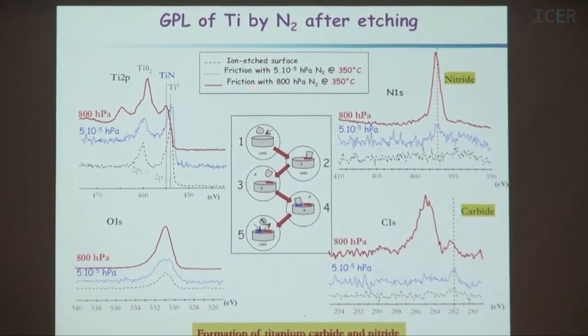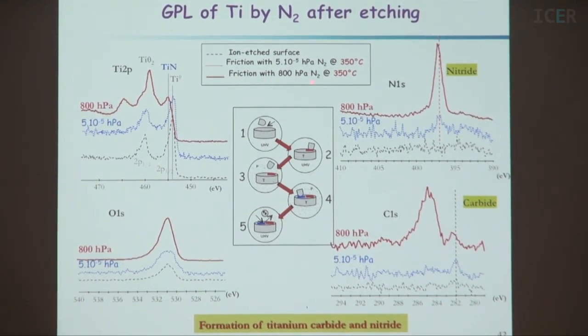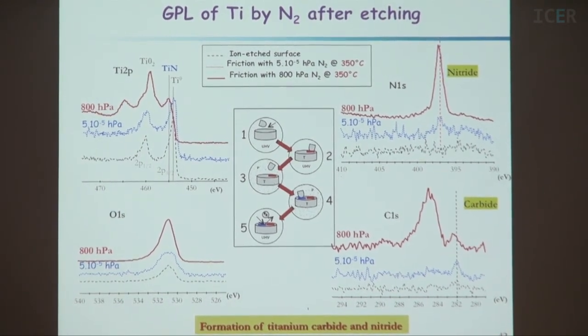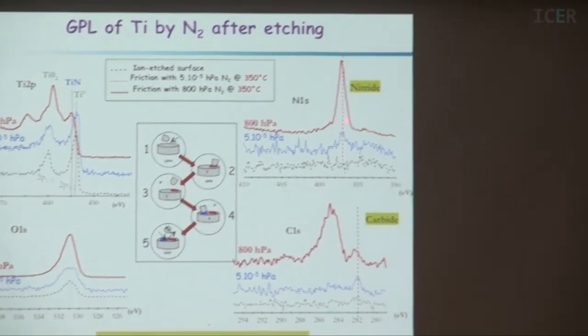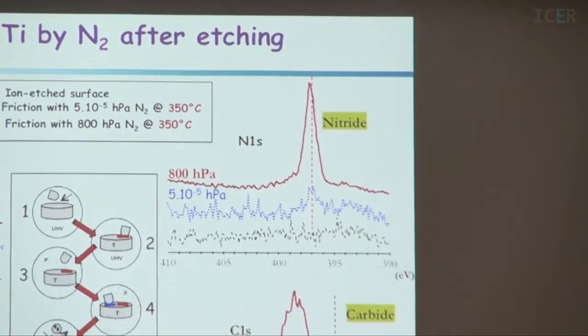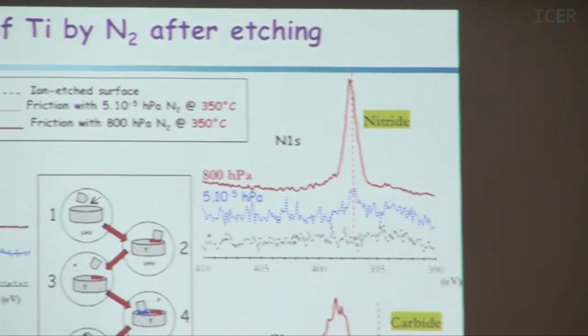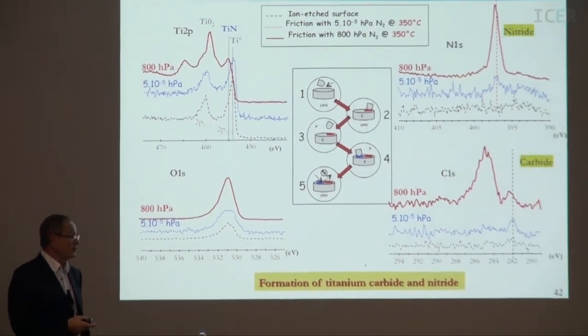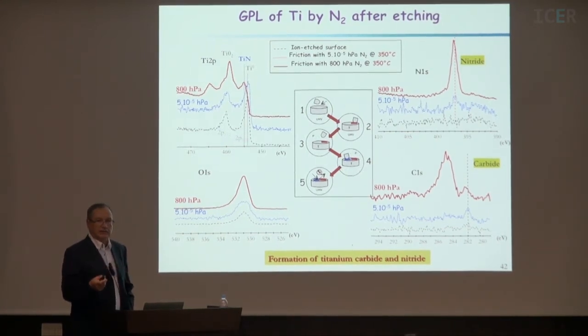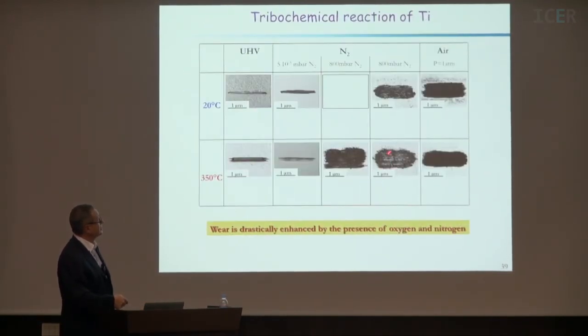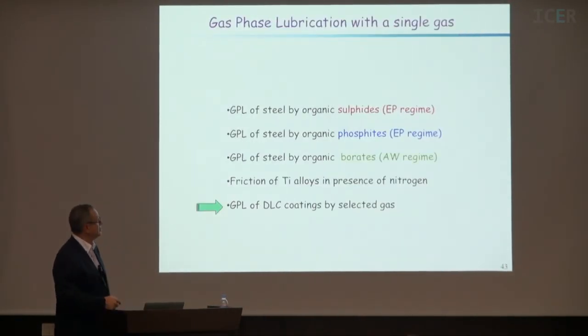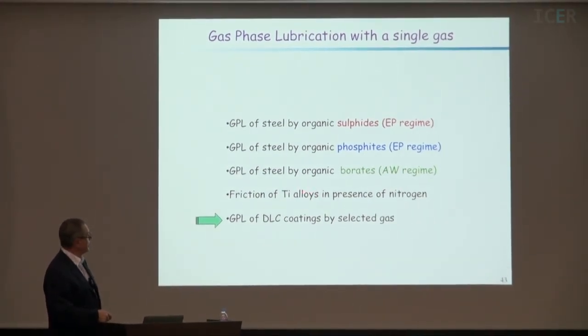But now we made the friction test with nitrogen. Friction with 800 hectopascal of nitrogen at 350 degrees. Typically, this is the temperature of the engines at this part of the engine. Here you can see that the nitride peak is coming. And not only the nitride, but the carbide peaks. The carbides come from some hydrocarbons also present in the nitrogen. So we were able to reproduce the formation of the nitride, and this nitride layer is very hard and provokes the wear of the alloy that you see here. So we explain this behavior.